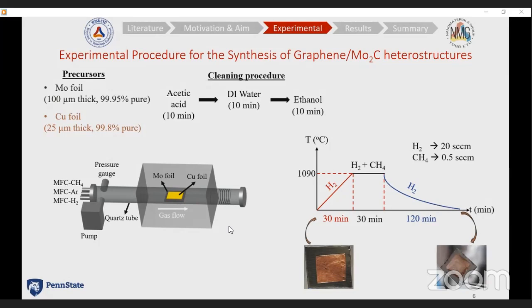And according to the literature, under these conditions, with a CH4 to hydrogen flow rate of 1/40, graphene along with molybdenum carbide is supposed to form. And actually, we observed a similar result.